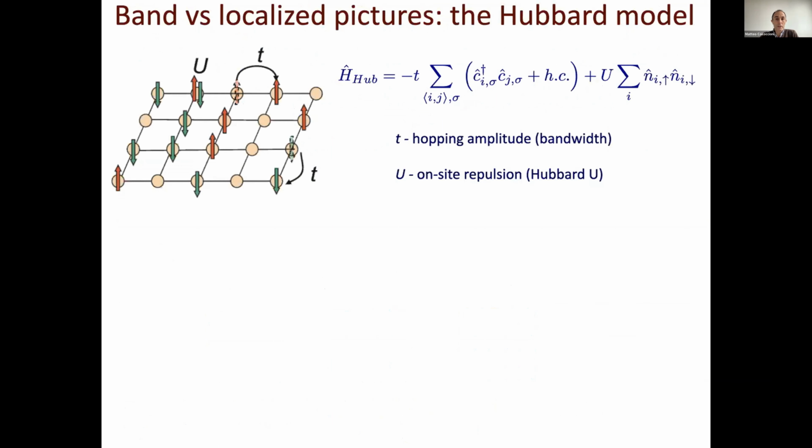Basically, we know that this is due to the fact that most of the approximations to the exchange correlation functional are based on the homogeneous electron gas, which of course favors a metallic ground state and over-delocalization of electrons, etc. So we want to use a model Hamiltonian, the Hubbard Hamiltonian, that's actually much better suited to capture also electronic correlation when the interaction between electrons becomes stronger.